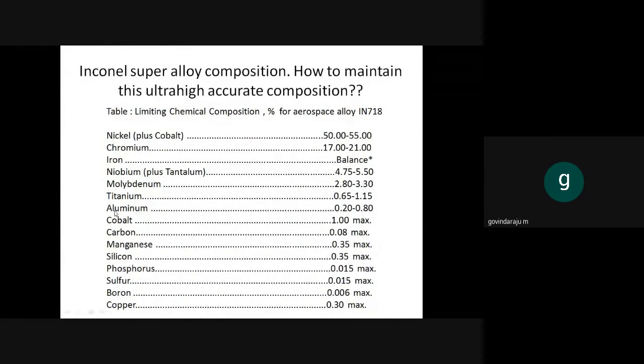What is the melting point of aluminum? It is 663 degrees Celsius. What is the melting point of this alloy? At what temperature is it melted? It's 1650 degrees Celsius. See, when an operation is carried out at 1650 degrees Celsius, you are adding a metal which melts at 673 degrees Celsius, and that too a meager amount, let us say 0.5%. In 1 ton, it is only 5 kg, is it not? When you do all the casting, finally you check that composition, the 0.5% aluminum may be only 0.3%, 0.2% might have evaporated. Or during adding, if you made any small mistake, after making this alloy, you have to throw out the entire piece.